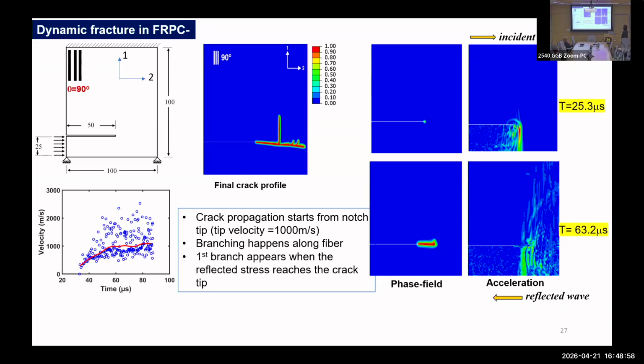And we saw precisely that the first branching happened when the compressive wave went and came back to this point. You see here the acceleration snapshot and the corresponding phase field evolution. When the first wave hit here, we see very minimal propagation as it continues to go. Remember, this part is purely shear driven. So the propagating wave is essentially a compression. So no normal crack, but shear.